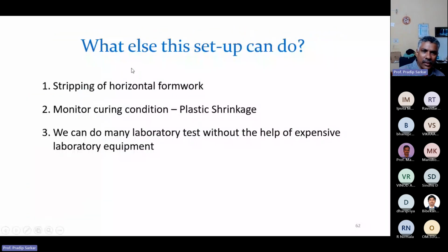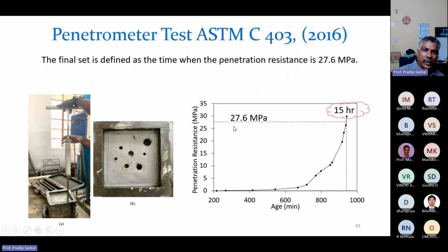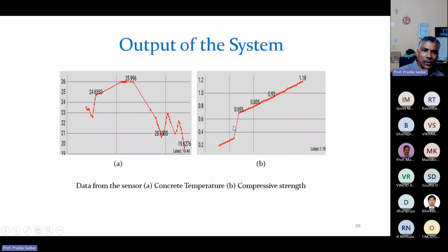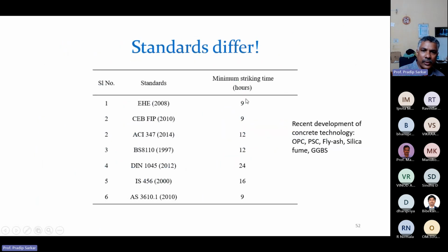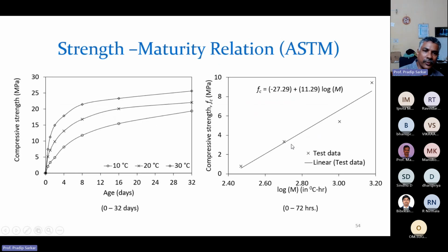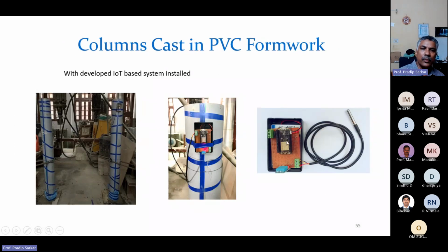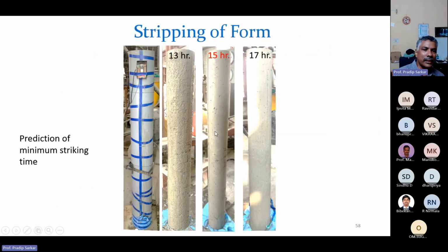Now if you look at the code once again, it gives you recommendations from 9 hours; the American standard says 12 hours, the British standard says 12 hours, and some other codes say 24 hours, and our Indian code says 16 hours when we can remove. But this data is again based on a particular type of concrete. Now here, for the type of concrete that we use, we can exactly see what strength is achieved by the concrete, and we can remove the formwork judiciously at a proper time, not very late and not very early.